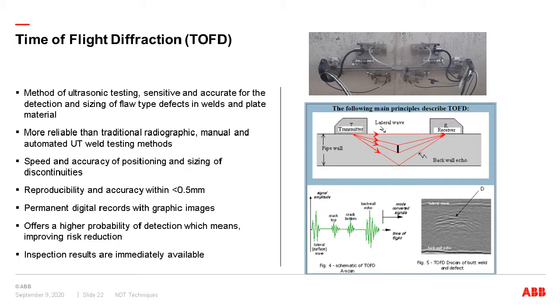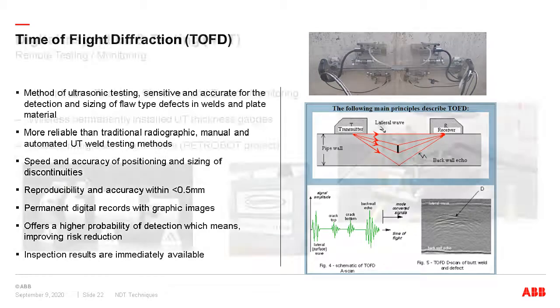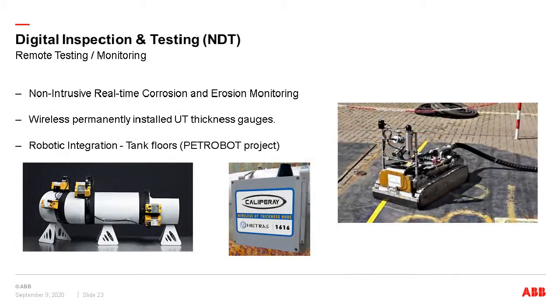It's very reliable. It's very reproducible, accuracy within 0.5 millimeter. It gives a permanent digital record, and it's better than the traditional radiographic and manual ultrasound techniques. You can see there, those are the two transducers, and you just roll it up the weld like that, and that can test the weld for any defects. So that's time of flight diffraction, quite a common one, very effective.